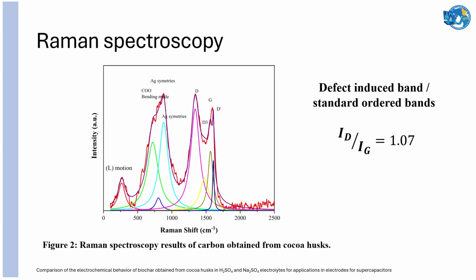The D' signal, also characteristic of disordered carbon, is also present. Additionally, the D3 signal corresponding to carbonaceous material according to the Sadezky model, and vibrational modes with Ag symmetries resulting from the presence of carbonates in the analyzed materials, as observed in the XRD results. These results confirm the information we showed in the X-ray diffraction analysis, because bands associated with carbonaceous materials with disordered or amorphous structures have been identified, favoring the formation of pores.